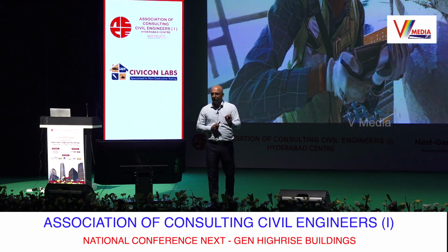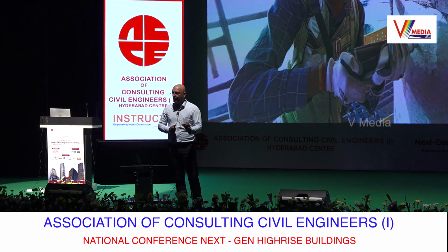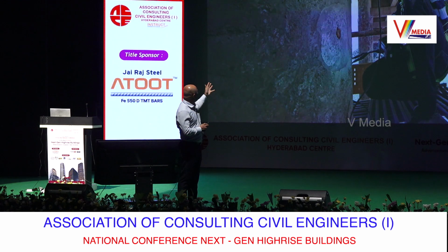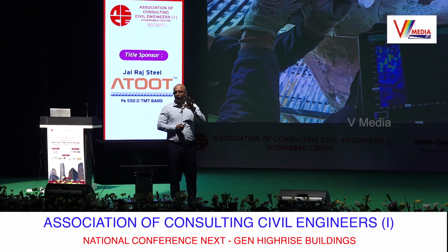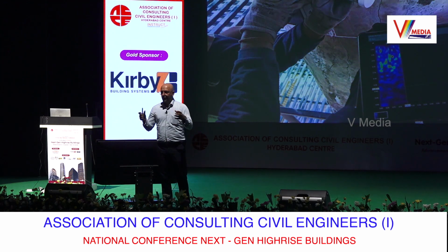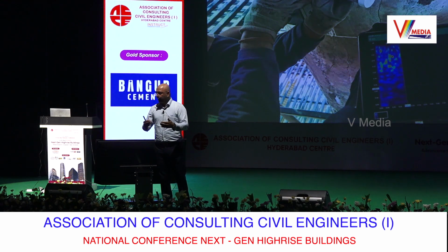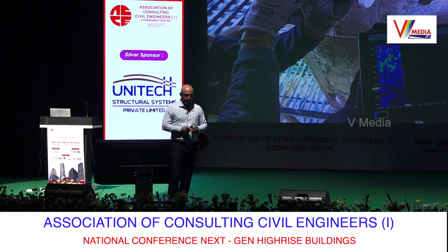So these are some of the very simple tests. What we did here was, we removed some part of the lining which was already damaged and performed some tests like hammer test, UPV, tomography also we did. So tomography, for those who don't know, is an advanced version of UPV. It has 24 channels, and what it does is it creates a complete slice-like image. So you'll be able to see inside the concrete where exactly your defects are.